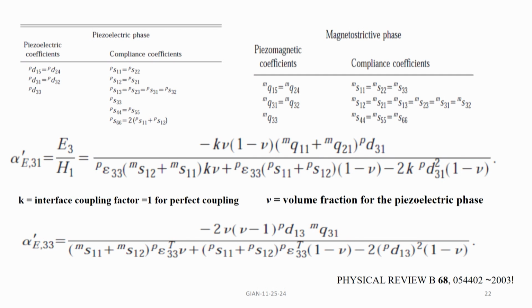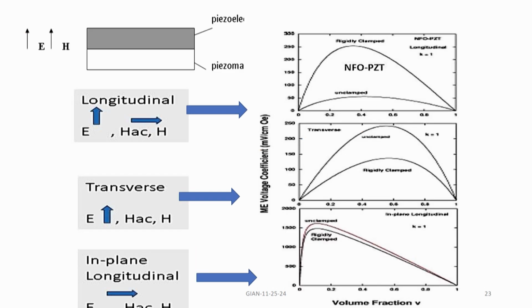So, it is a bit complicated expression, but what it comes down to is these are the key terms Q and D. So, this is the piezoelectric coupling coefficient. It couples to what happens due to the in-plane AC magnetic field. And the one here is for all the fields perpendicular to the plane, and these are some examples for very selected system of bilayer composites.